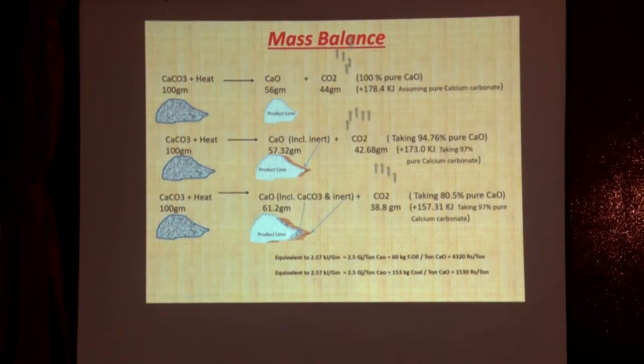That means if you are producing a ton, the theoretical fuel requirement at 80% purity will be 2.57 gigajoule per ton, or you can say 60 kg of furnace oil, or in terms of coal, 153 kg of coal, if it has a GCV of 4500. This is the fuel requirement. I am just bringing the stoichiometry so that you can correlate at what efficiency the rotary lime kiln is running.